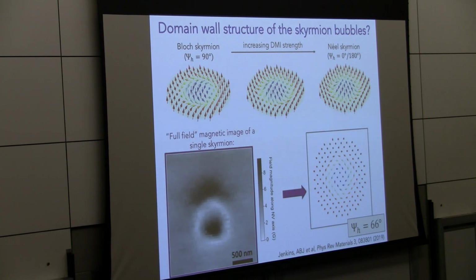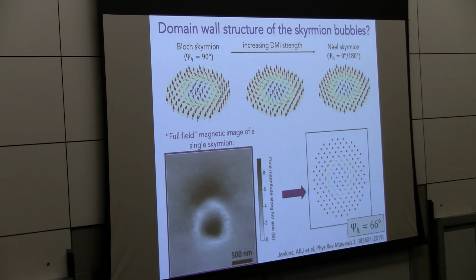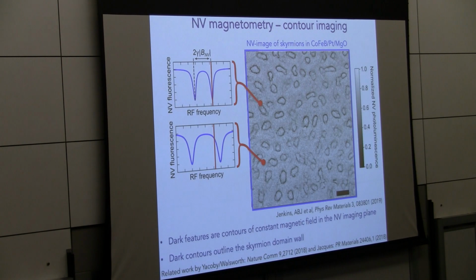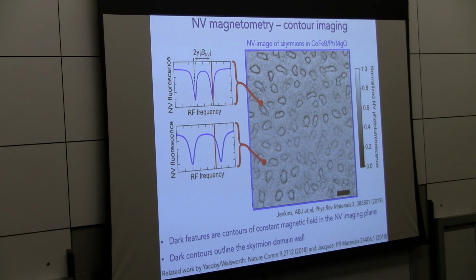So at each point in the scan, we're taking a full ESR sweep to map the splitting to get the full magnetic field. One can do that, but one can go a little bit more quickly by taking what's called a contour image, which is what I show here. Just really briefly, how that's taken is we fix the frequency of our applied microwaves to one value, and we monitor the fluorescence of the NV as we move the tip around, and it experiences different magnetic fields.